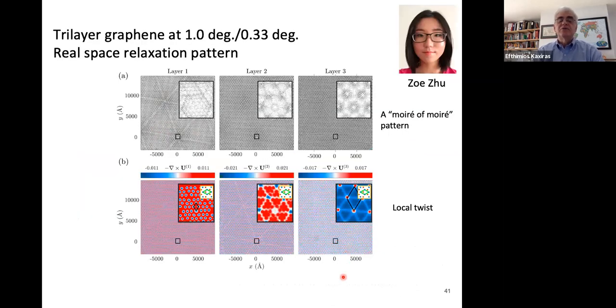Well, this is not an easy system to analyze because of the complexity that I mentioned a moment ago. And fortunately, I have another really amazing student, Zoe Zhu, who is involved in these calculations. So this is an example of Zoe's work in collaboration with Stephen and Shang and other members of my group, showing this kind of pattern, which we call a moiré of moiré. So you have two sets of moiré patterns because of the two different pairs on top of each other, and you get very interesting additional effects in the atomic position. So these are pictures of the atomic positions involved and the local twist angles and so on. But the most interesting aspect is what happens to the electronic states associated with this. By the way, these are really tour de force calculations that Zoe was able to carry out, and she really is fearless. I mean, this is a difficult problem.